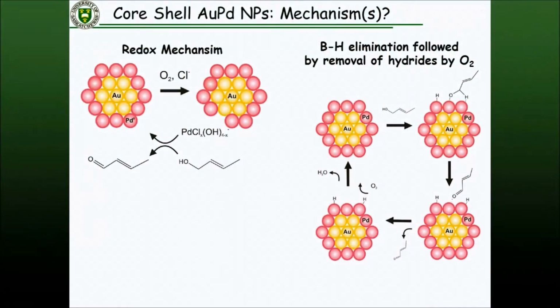We kept trying to understand the mechanism of this and realized there are two possible mechanisms here. One of them would be a redox mechanism. We know palladium-2 salts react stoichiometrically with the allylic alcohol. So potentially, if the palladium could reoxidize, for example in the presence of a halide, we could have a redox cycle in which the palladium is essentially going from the particle back into solution over and over again.